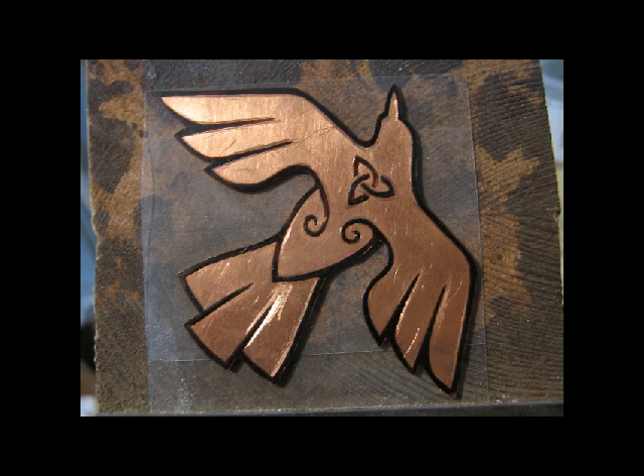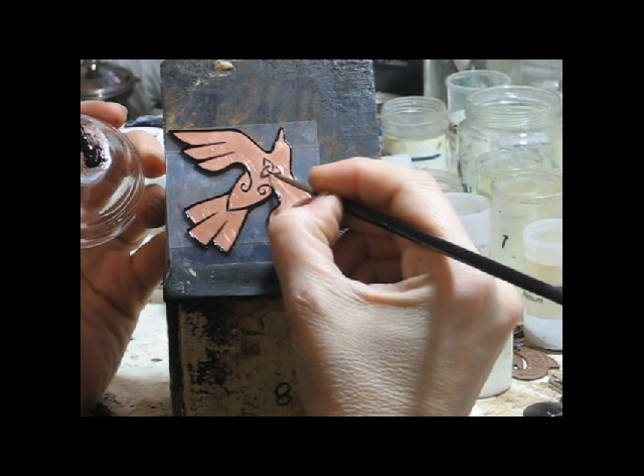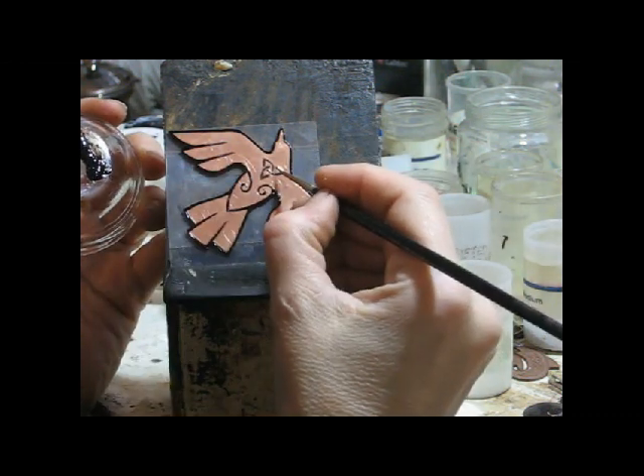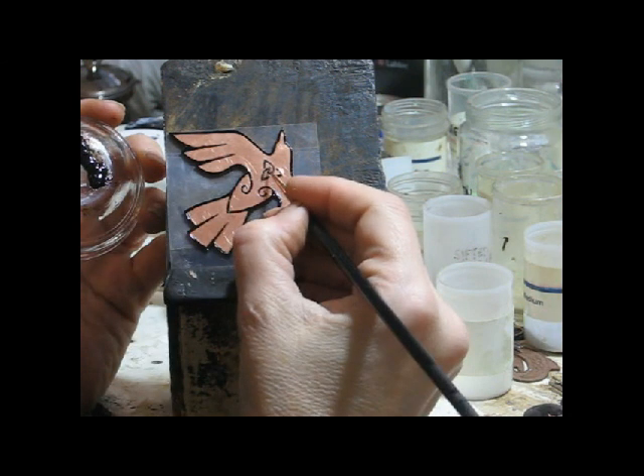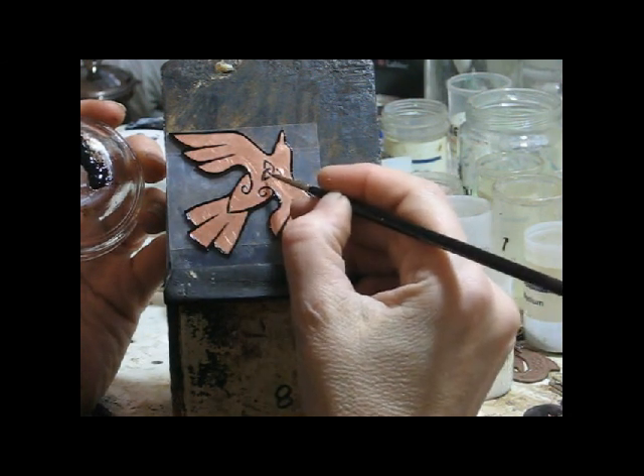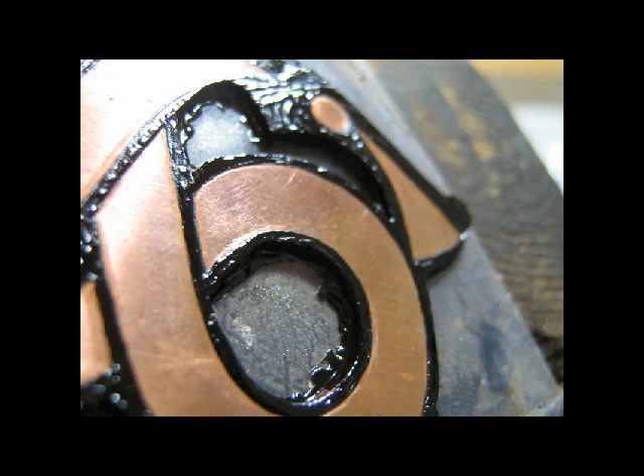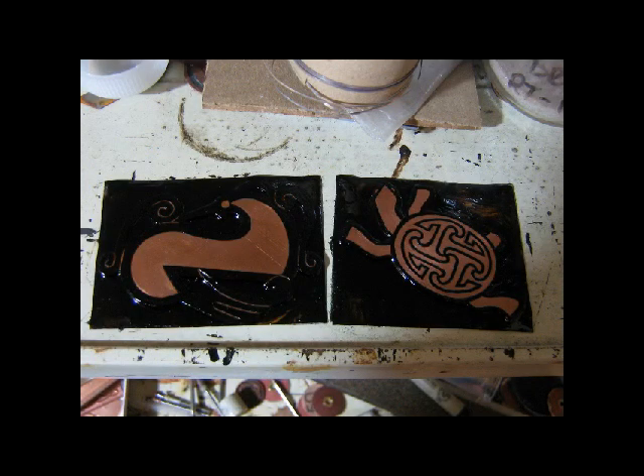After I have them cleaned, I put a piece of tape on the back to resist the acid, and then I paint a second coat. The first coat is never a completely covering coat — there are often little pinholes invisible to the naked eye — so the best practice is to put a second coat over the whole thing to make sure every area of copper is completely covered. I also do the edges, which are quite vulnerable, giving them two coats: once when I do the top coat, and again when I coat the back with a diluted asphalt mixture.